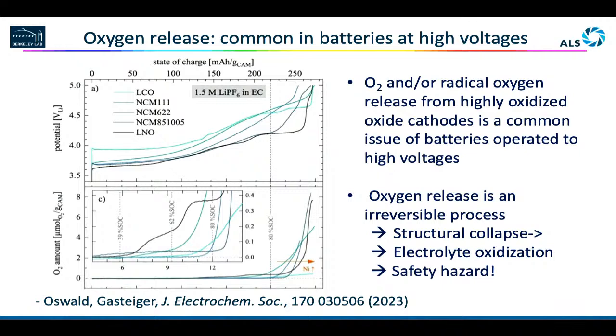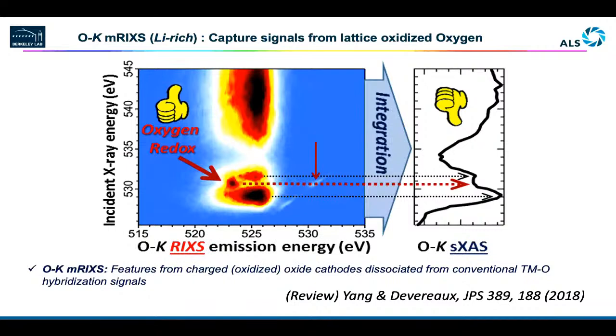And if you look at the gas release here, obviously this is not a very good thing. You have gas release. It's completely irreversible. So that's not something we want to have. And lithium cobalt oxide, the very first positive electrode, behaves almost like the best of the best in this whole set of materials. I'm not sure if Professor Goodenough was just lucky to hit this, or we are just doing such lousy work after 30 years that we just couldn't break this through. So anyway, keep in mind, there is oxidation of oxygen in the form of oxygen release, completely irreversible.